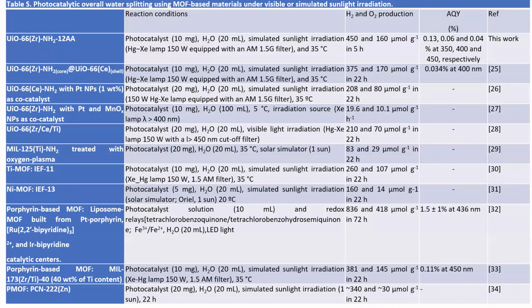So we wanted to compare our data with the literature data. This table clearly shows that our material shows very high activity after 22 hours. There is another paper, a porphyrin based MOF, which exhibits 836 and 418. This is after 72 hours, and here they have used a platinum porphyrin and a ruthenium bipyridyl complex and an iridium bipyridyl complex. So the system was a little bit complex here. Whereas in our case, we have just taken a very simple catalyst and it has given better activity.